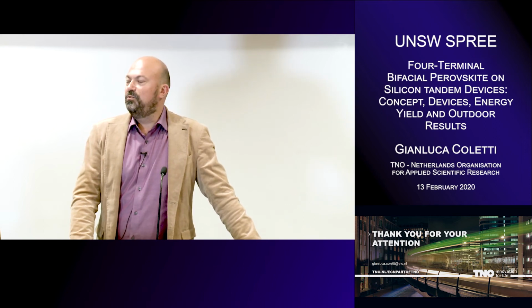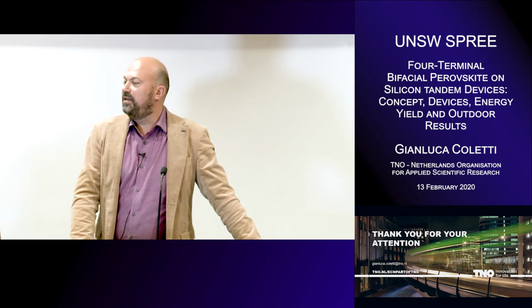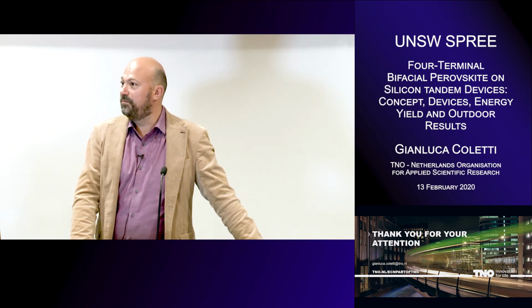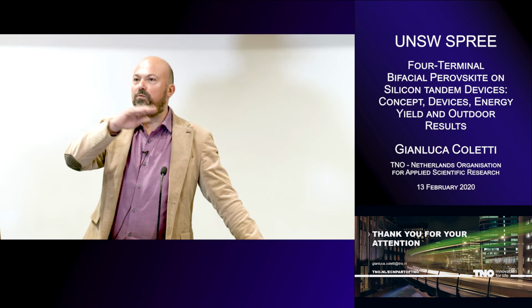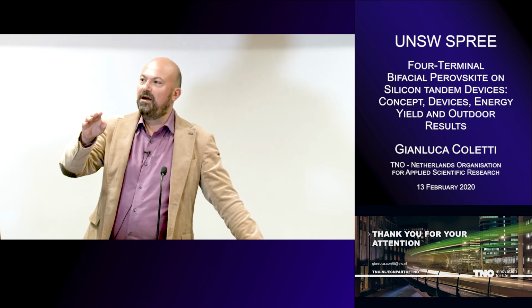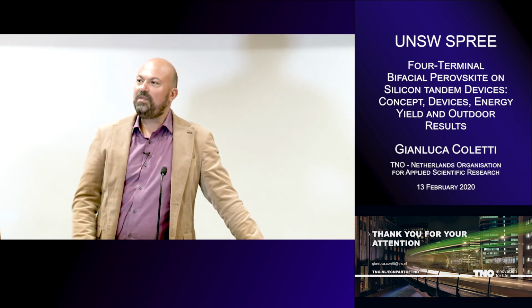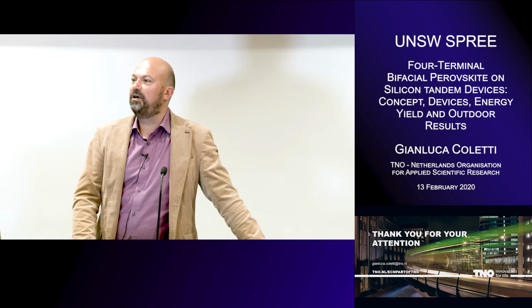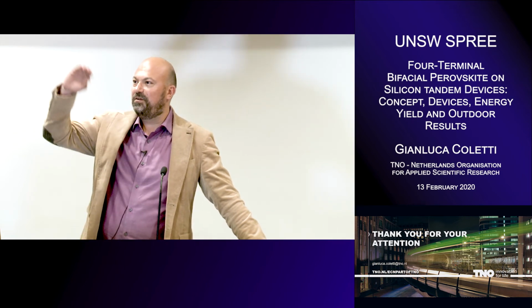Well, this has to do with the perovskite. Essentially, we have noticed often that when you do an annealing or when you put them under the light in certain conditions, they improve. And that's what we see. But anyhow, we consider it stable with respect to the initial condition. But it's common. We have seen also at other players that you have this increase, not always.